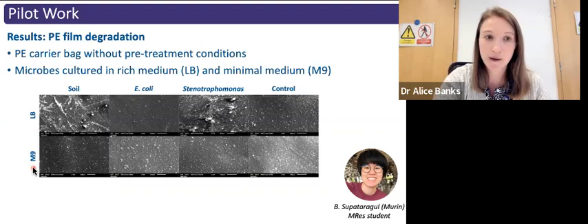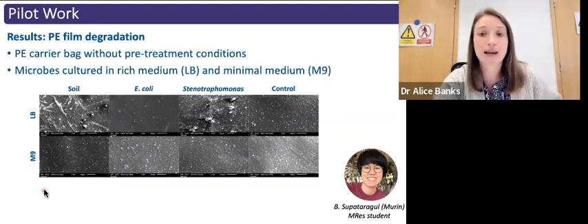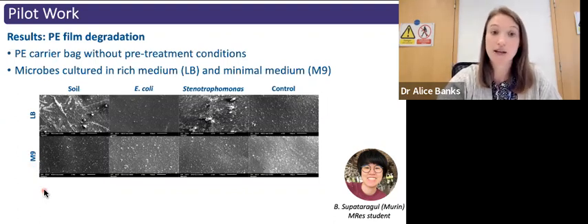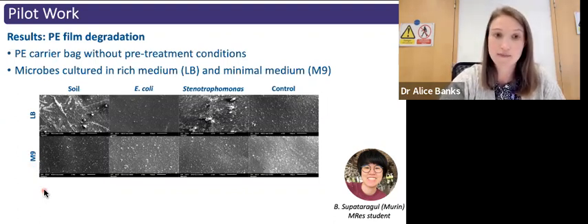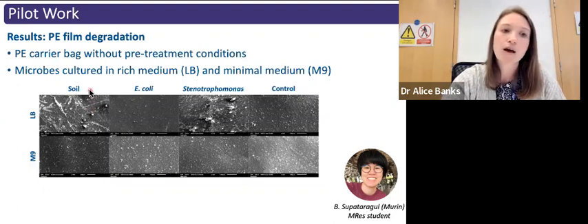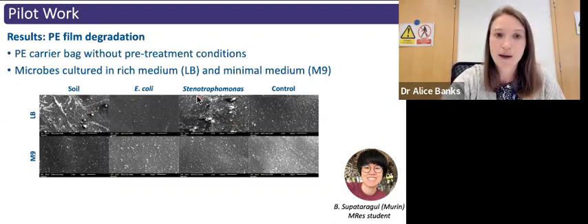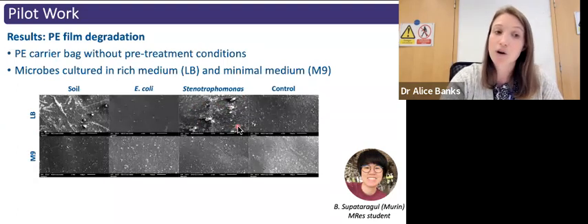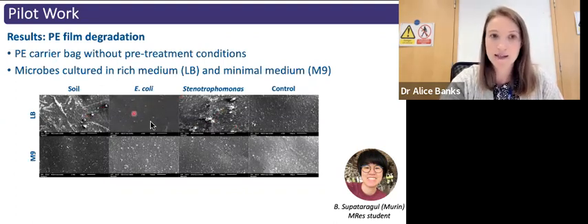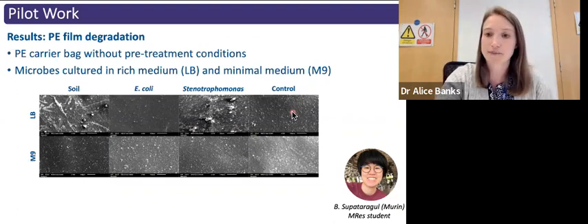And after an incubation period, we then examined these films using scanning electron microscopy to look at any changes in the surface morphology of these polyethylene films. And what the SEM showed was that it was fairly clear that for bacteria that were isolated from the soil and also the bacterium Stenotrophomonas, we saw quite marked changes when the bacteria were grown in the rich substrate with the plastic present as well. And there were some holes, some corrosion, and quite significant change to the plastics in both of these instances that we didn't see in our negative control with E. coli. And we also didn't see it where we just had the polyethylene in the liquid broth under incubation.